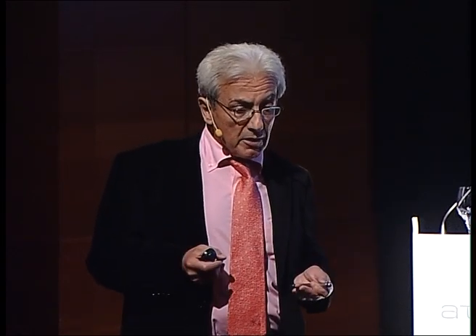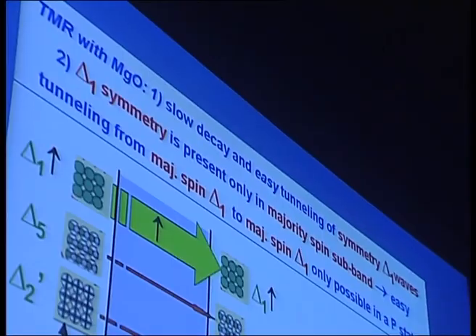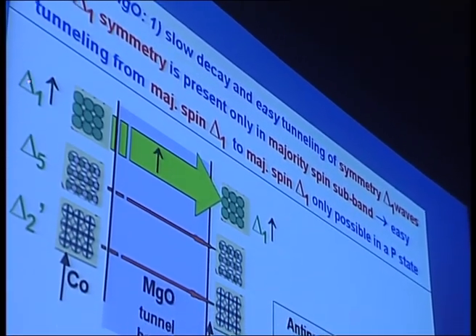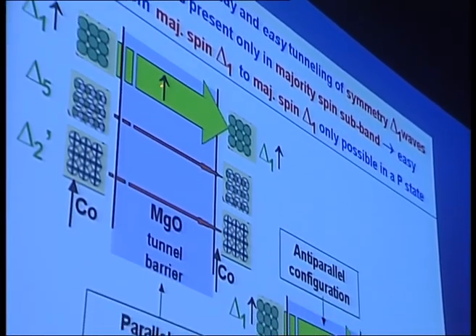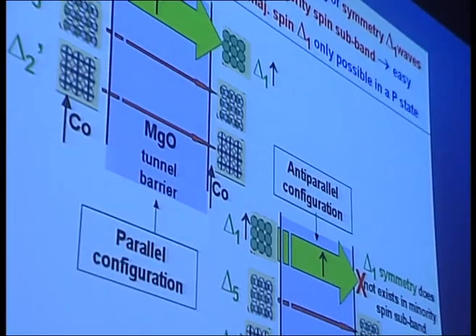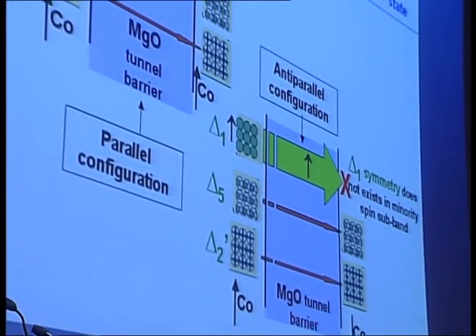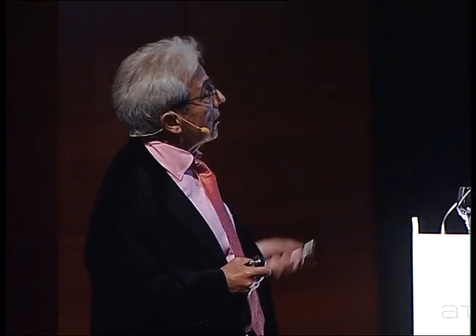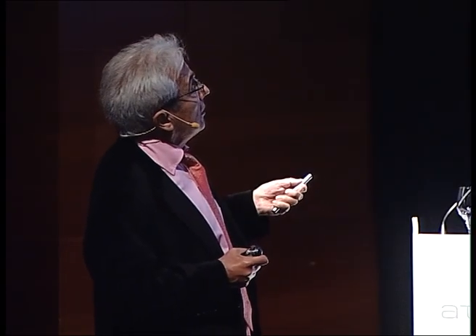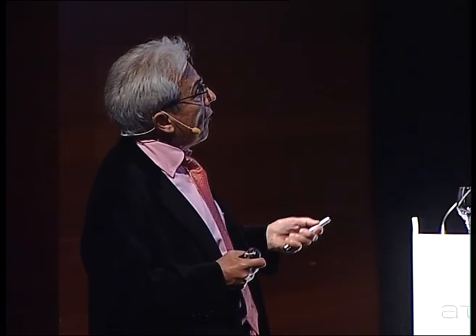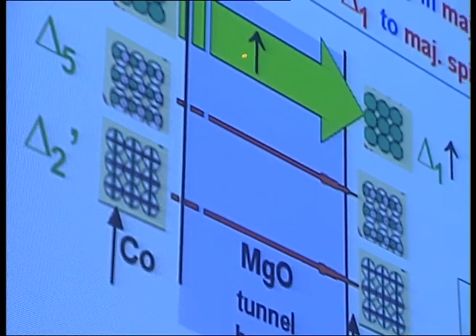In a single crystal insulating material, the transport is by evanescent waves, decreasing exponentially. But in a crystal, these waves are of different symmetry, like in any crystal. So in this case, delta 1, delta 5, delta 2. And it occurs that in MgO, delta 1 is a much better channel. The wave of symmetry delta 1 decreases only slowly as a function of the distance, and so this is the good channel for the transport of electrons from one side to the other. Also in the metal, there are waves of symmetry delta 1, delta 5, delta 2, and if the interface is of high quality, again the nanotechnologies, the delta 1 is connected to the evanescent wave of symmetry delta 1.